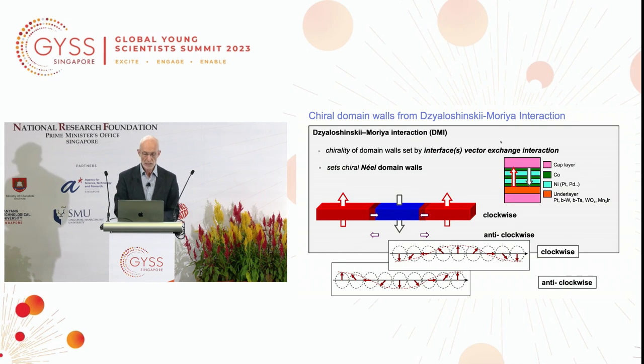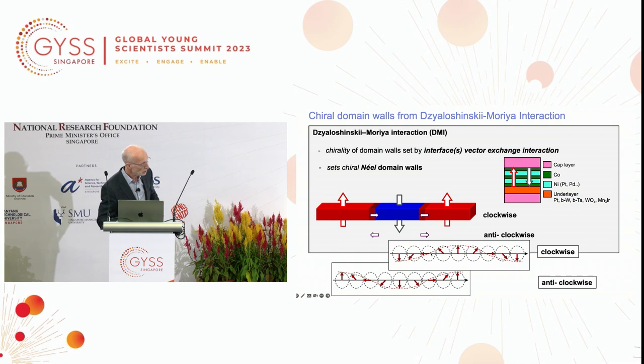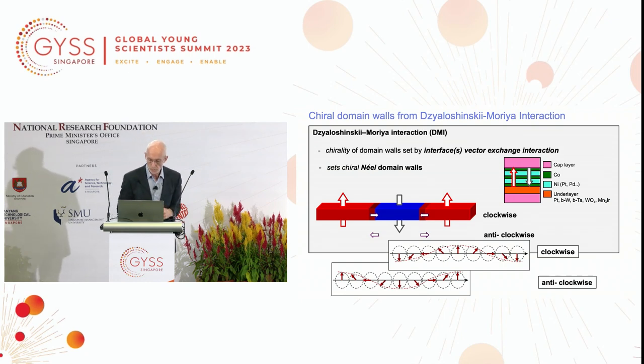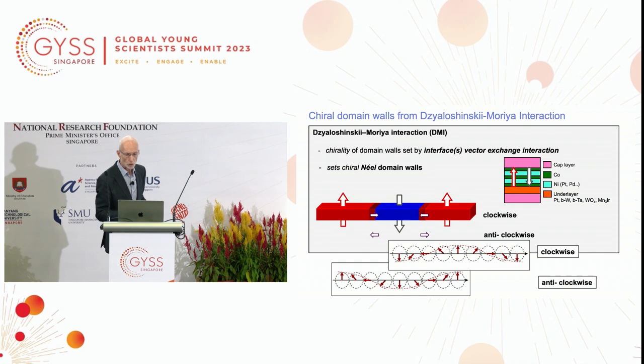Another chiral phenomenon is the domain wall itself. So going back to this very simple picture, you can see here is the racetrack, magnetization here pointing in the red direction up, blue direction down, but in between the magnetization rotates in a very special way. It will rotate in either a clockwise or an anti-clockwise direction. You can see at the bottom, here is the magnetization pointing down, and as it rotates to the up direction, you see in the middle, the magnetic moment here is pointing to the left, but when it rotates from an up to a down direction, that magnetic moment points to the right, and it turns out it has a chirality. This is introduced by the same material in which we see this spin Hall effect.